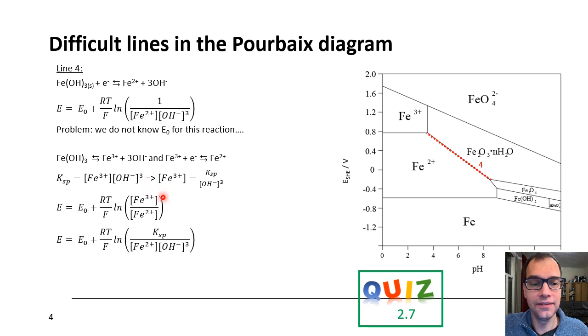And we can basically fill in the first equation into the second equation. So the iron 3 concentration is the solubility product divided by the OH minus concentration to the power 3. And then you get this equation. And now in this equation, E0 actually belongs to the iron 3 iron 2 reaction and not to the reaction on the top. Also, if you compare this reaction to that reaction, you see that they are not exactly the same. The Ksp is here.